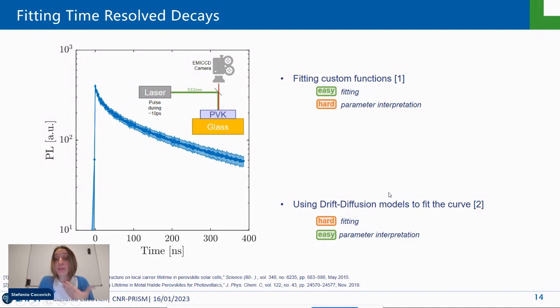In this case, the parameter interpretation is quite easy because they are based on physical models, but on the other side, the fitting can be quite challenging. First, because there can be some connection, some relationship between the different parameters, so they are not independent. And also, if we want to apply such kind of models on a map, by fitting 1,000 pixels, this is computationally too heavy.